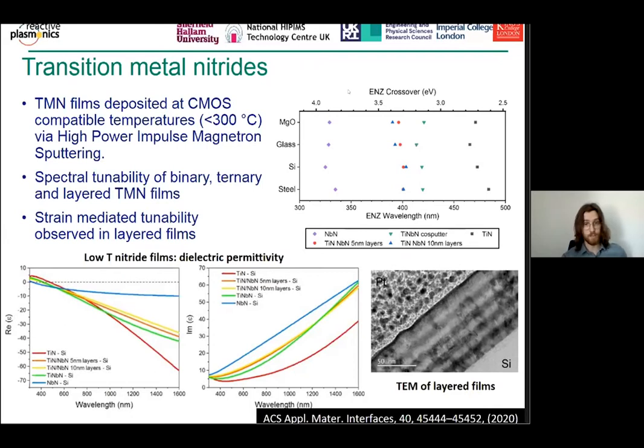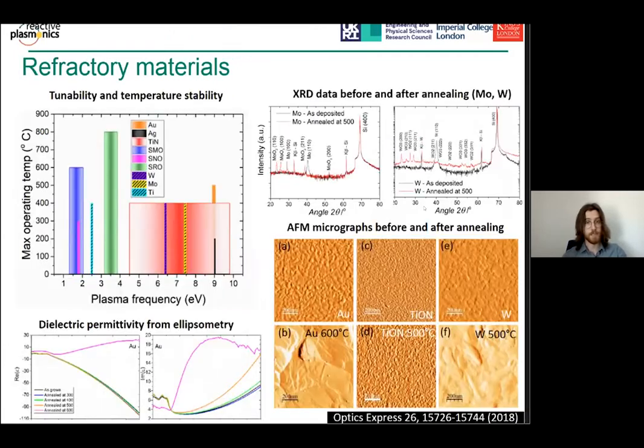In this work, we also investigated the tunability between niobium nitride and titanium nitride ternary films. So niobium nitride has a plasma frequency in the UV, titanium nitride in the visible, and we showed that if we deposit co-sputtered films, we can tune the plasma frequency between the UV and the visible. We also deposited layered films and found that layered films of titanium nitride and niobium nitride display a blue shift compared to co-sputtered films of the same stoichiometry. So this is potentially interesting and another degree of freedom when it comes to tunability of these films. So that was mostly spectral tunability and understanding the deposition process of these films.